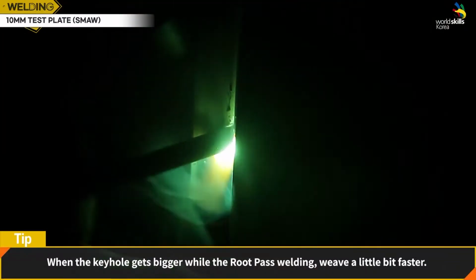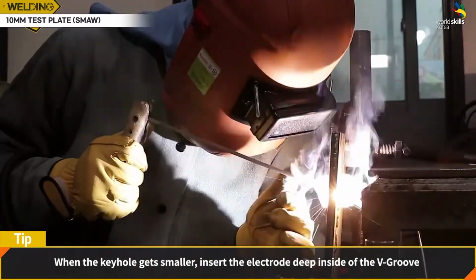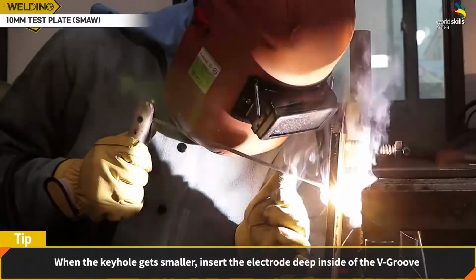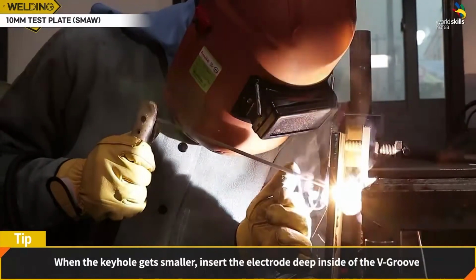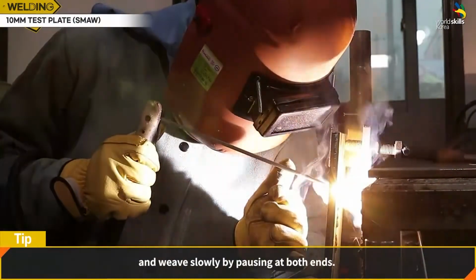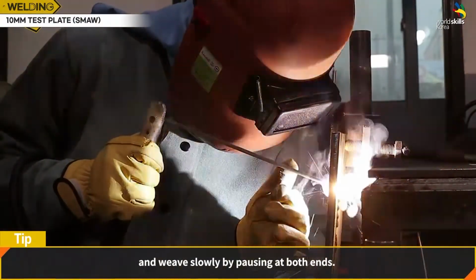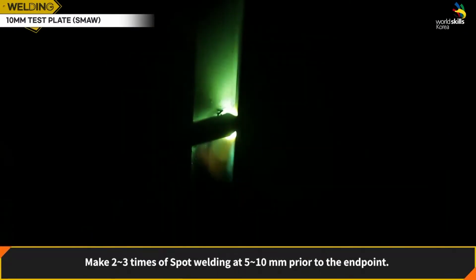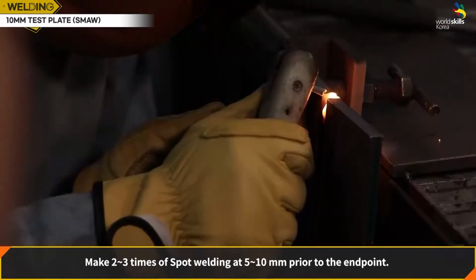When the keyhole gets bigger while root pass welding, weave a little bit faster. When the keyhole gets smaller, insert the electrode deep inside of the V-groove and weave slowly, pausing at both ends. Make 2 to 3 spot welds at 5 to 10 millimeters prior to the end point.